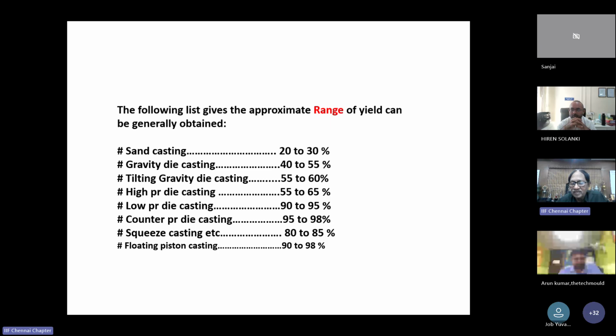Counter pressure die casting is also excellent, used for thin walls and also big castings, with 95 to 98% yield. Excellent yield, but it requires a lot of investment. Squeeze casting also 80 to 85%, used mainly for very thick castings where you don't want the blowholes or shrinkages. All are squeezed out.